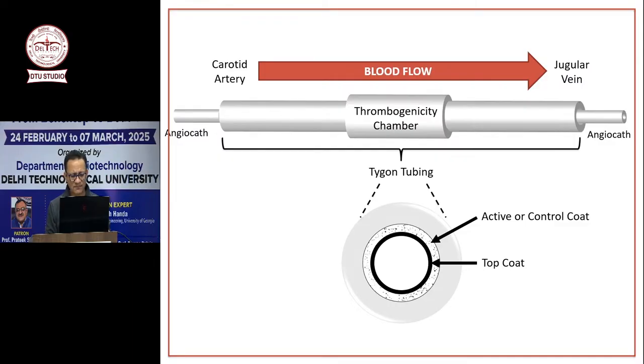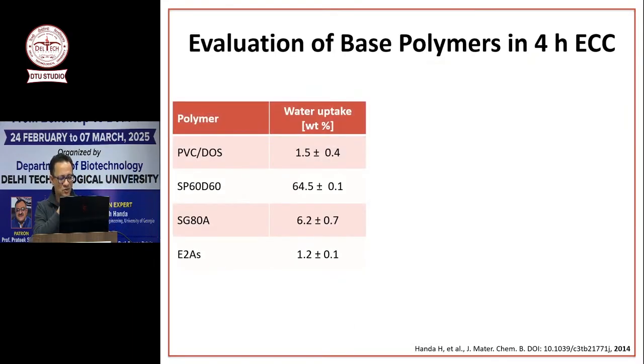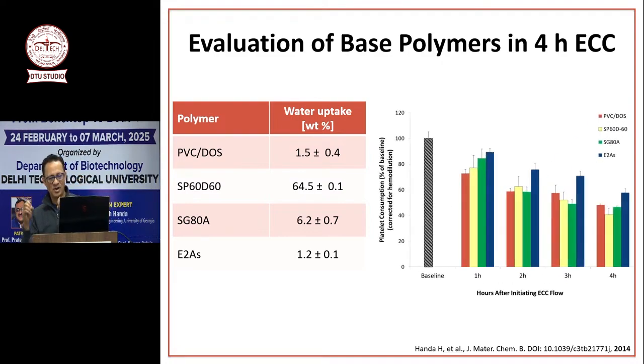Let me go a little bit back for this study. A few years ago in 2014, first we wanted to see, forget the NO donor, what is the best polymer that is most hemocompatible by itself. So we did a 4-hour ECC study where we saw that E2AS polymer, a copolymer of silicone rubber and polyurethane, was the best.